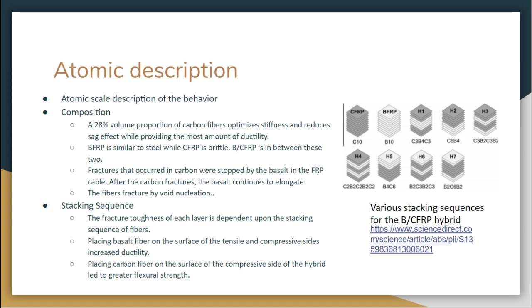So moving on from composition, another thing to think about is stacking sequences. So there are many stacking sequences that can be created with carbon and basalt fibers. These stacking sequences had a great effect when the samples underwent flexural loading, which led to both tensile and compressive stresses. One conclusion that we found from these stacking sequences was that when carbon fibers were placed at the surface that was going through compressive stress, the strength of that material increased.